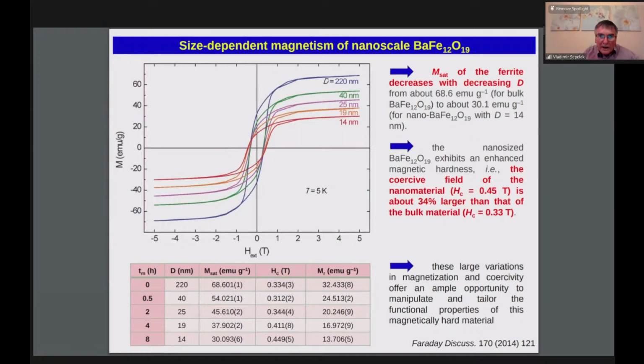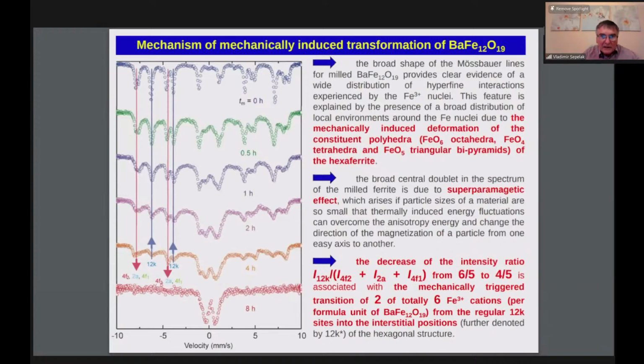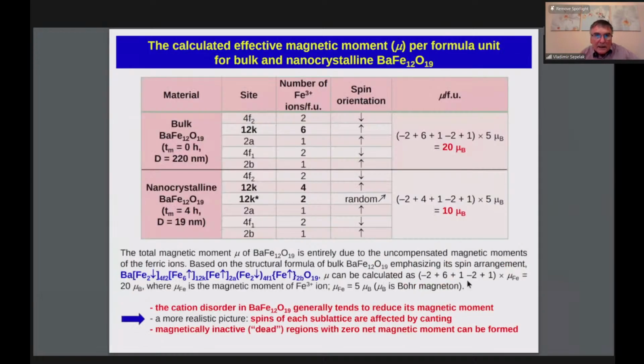behavior, we have performed X-ray diffraction studies and Mössbauer spectroscopic studies, and we see what is happening if we go to nano materials from bulk material. We see that the intensity ratio changes, and that means some of the cations from 12K octahedral sites go to some interstitial sites. We say 12K star, and if we calculate the magnetic moment for such configuration obtained from Mössbauer spectroscopy, we see a real decrease of magnetization for nanocrystalline barium hexaferrite.